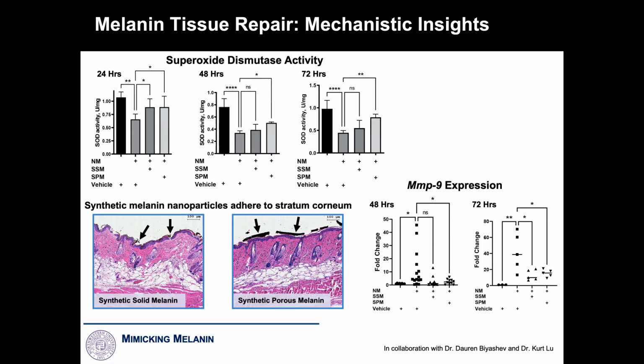And this is the last biochemical piece of data that I'll show you, is that really excitingly, these downstream signals for inflammation. This is a matrix metalloproteinase. This is upregulated in all kinds of organ systems. When people have heart attacks, their heart fills with these proteases that try to remodel your tissue. If you were to cut yourself with a scalpel, these would be upregulated in order to control scar formation. So it's a prevalent signal in all of our organs that's indicative of a late downstream upregulation of the inflammatory response. When we treat with melanin, right, as opposed to when we don't, we get this massive reduction in the melanin treated controls. We see this big reduction in downstream inflammation, which kind of proves it biochemically.